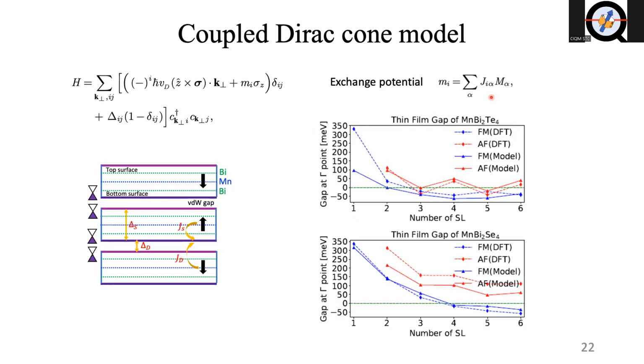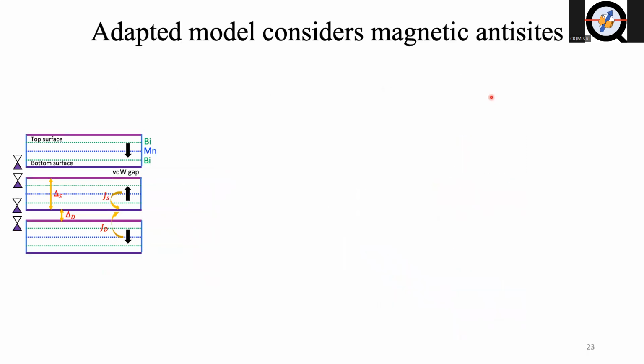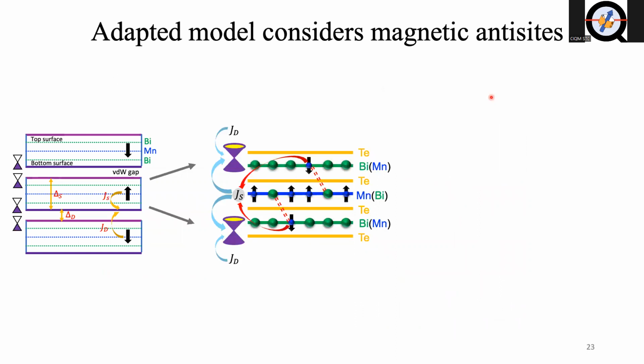So here is our calculated result. In the thin film case, we can see that except for the first topological layers, for all the other topological layers, the DFT calculation compares pretty well with our model calculation. So they compare reasonably well. So then after we have such a Dirac model, in our specific experimental study, we adapted this model to take into account those magnetic anti-site defects. The model was first proposed for only the case of pristine thin films, but let's now take a look at what happens after we consider those magnetic anti-site defects.